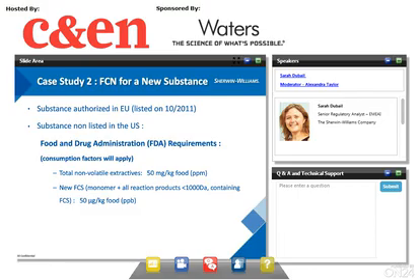So those were determined. The target for the new coating was to get a level of migration below 50 ppb for the sum of the substance and all the reaction products derived from it. And if the coating met the limit, that would allow us to build a dossier without needing any further toxicological data than the ones which were already available for the food contact substance.